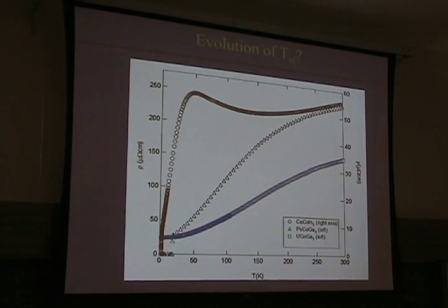And here, why should we think that the spin fluctuation temperature is changed when you go to CeCoIn5 with the plutonium case? You can see that's the resistivity. So if we take the coherence temperature as a measure of the spin fluctuation temperature, you can see that you have a very well-developed maximum at 50 K for cobalt that seems to be shifted to higher temperature when you go to the plutonium, cobalt, gallium-5, right?